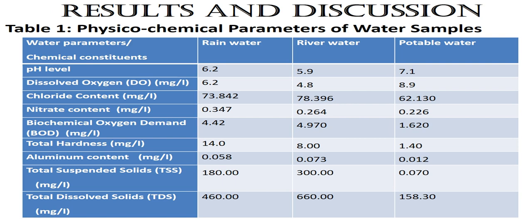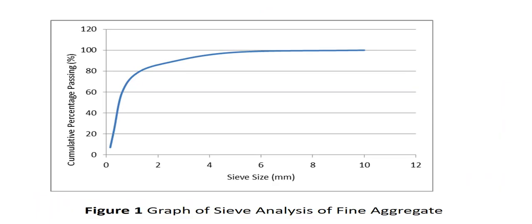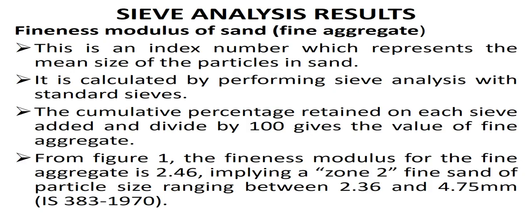Table 1 shows the physicochemical parameters of water samples. Figure 1 shows the graph of sieve analysis of fine aggregates. Sieve analysis results: fineness modulus of sand as a fine aggregate. Fineness modulus is an index number which represents the mean size of the particles in sand. It is calculated by performing sieve analysis with standard sieves. The cumulative percentage retained on each sieve added and divided by 100 gives the value of fine aggregate. From figure 1, the fineness modulus for the fine aggregate is 2.46, implying a zone 2 fine sand of particle size ranging between 2.36 and 4.75 mm.